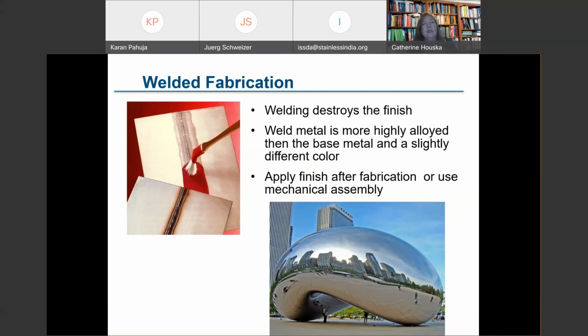So I'm showing the cloud gate again, and this is again something I consulted on. When they started to weld this together, the fabricator realized as they polished this to a perfect mirror on those welds that there was a color difference and the welds were showing. That's because weld metal is more highly alloyed than the metal that is being welded. So they had to have a welding product supplier do some experimentation and come up with a weld metal to match the base metal, because otherwise we would have been able to see all of those weld lines. They would have been faint, but they were there.